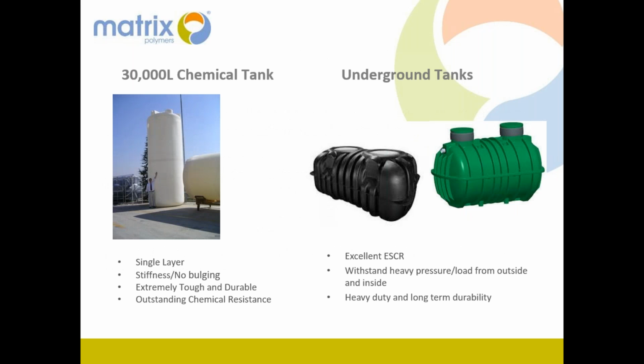So typical applications: underground tanks. You can see that very tall tank, which is a single layer tank, with no stiffness issues, no bulging, extremely tough and durable. These are typically chemical tanks, so it has outstanding chemical resistance. There are no structural features in the design; it's a single layer tank, and that is possible only because of the features of a hexene material. Underground tanks withstand heavy pressure load from outside and inside, and have to be heavy duty with long-term durability. ESCR is very important, so all these things are taken care of by a good hexene resin.